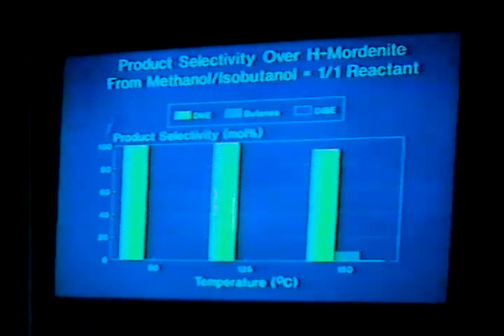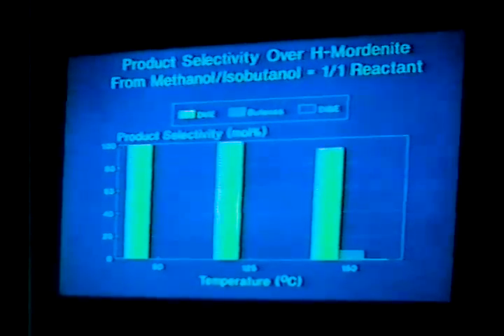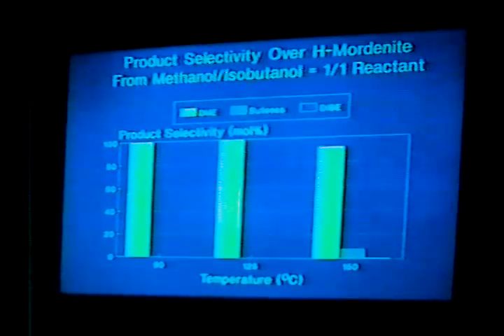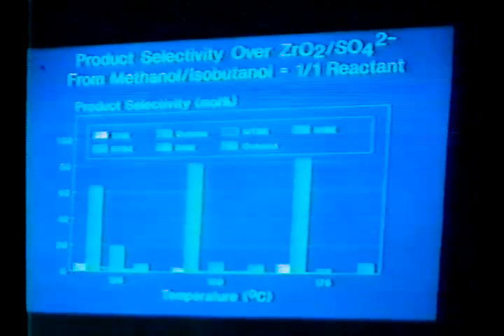H-mordenite will make selectively in that mixture DME. This is interesting because it indicates that the protons of H-mordenite at these low temperatures, this is a low temperature catalysis, are not accessible to isobutanol, despite the fact that the large channels of H-mordenite are accessible to both alcohols. And in fact, H-ZSM-5 shows poor selectivity with respect to these reactions because it has the acid sites exposed at intersections, whereas in mordenite the acid sites are buried in the side channels at low temperatures. Only at high temperatures will the acid proton travel inside the larger channel and carry out these reactions which are so well known in H-mordenite.